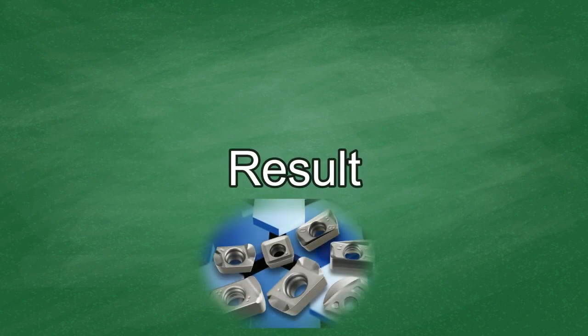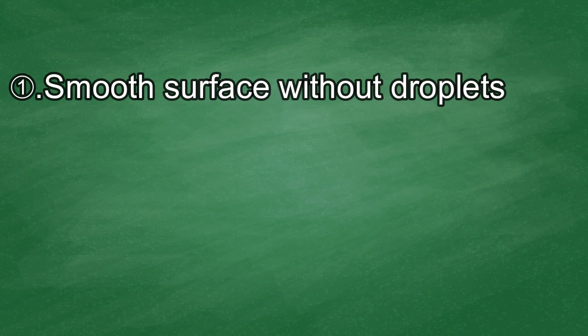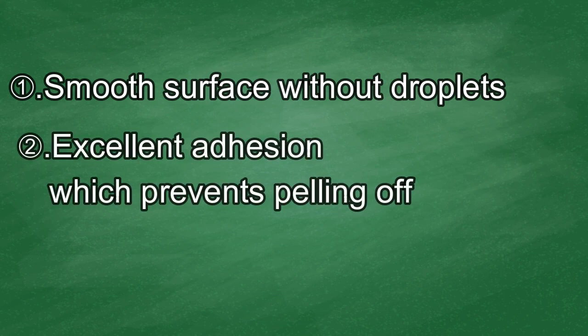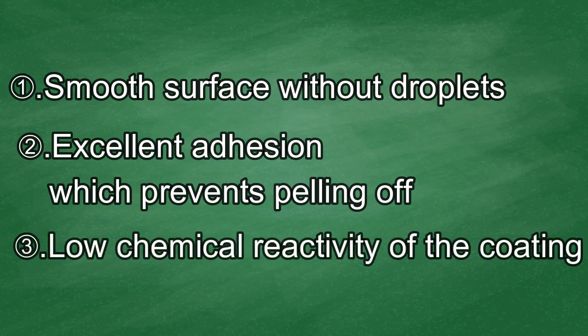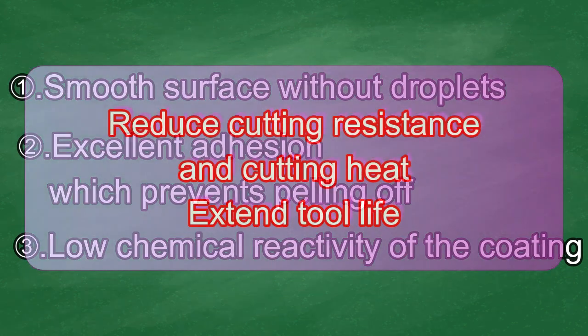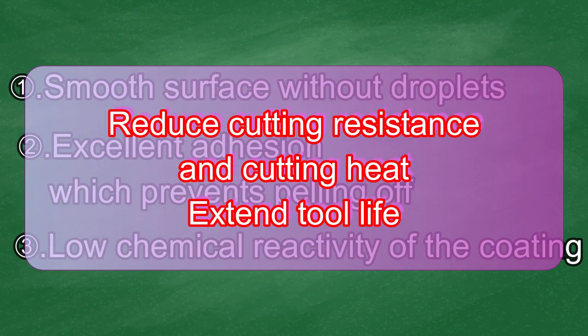Here is a summary of the DS1 coating that we introduced today. Smooth surfaces with no droplets, excellent adhesion, and low chemical reactivity of the coating, which prevents peeling off, reduce cutting resistance and cutting heat and extend tool life. This is a presentation of tool life improvement with DS1 coatings.